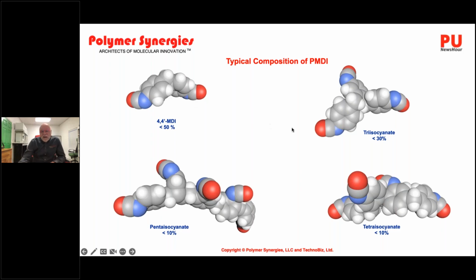So this molecule is going to react differently than this molecule, which is going to react differently than this molecule, which is going to react differently from the pentaisocyanate molecule. So they're all going to react differently. In addition to that, the size and the shape of these molecules will affect the order of the rigid domain, which will affect the properties that you're going to measure for your polyurethane. So these are things to keep in mind when you're formulating. The size and the shape and the reactivity of the molecule will affect the properties and performances. And if you take one of the other classes that Technobiz offers on isocyanate chemistry or formulating moisture cure adhesives or whatever, I talk in great depth about these types of structure property relationships.